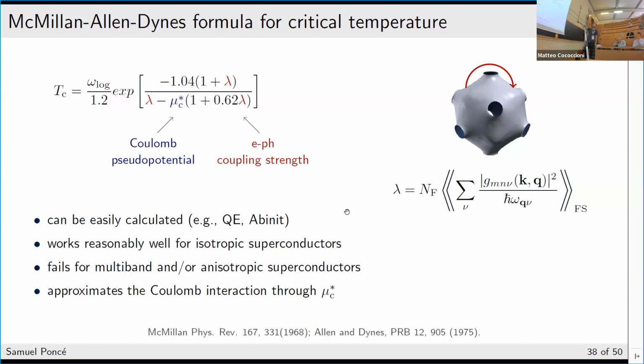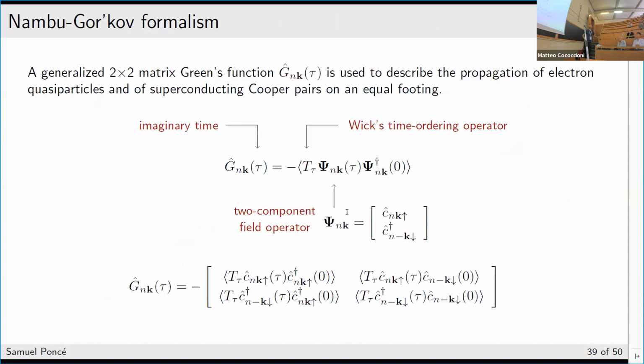It works well for isotropic superconductors, but it has some limitations. Since it's only an integral, you have no resolution. So for example, if you have anisotropic superconductors, you will not describe them very well because it's just one number. And then also this Coulomb interaction is approximated with one number. Okay, and so what can we do to improve this?